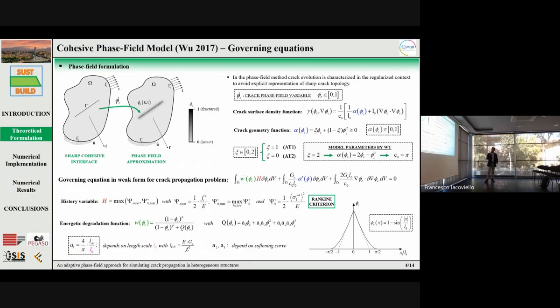The governing equation in weak form for the crack propagation problem is the following, where H is the history variable and W represents the energy degradation function, which are evaluated through the following expressions. The function W also depends on three parameters, A1, A2, and A3. In particular, A1 is calculated via this formula and depends on both the length scale L0 and the characteristic length LC, while A2 and A3 depend on the softening curve.